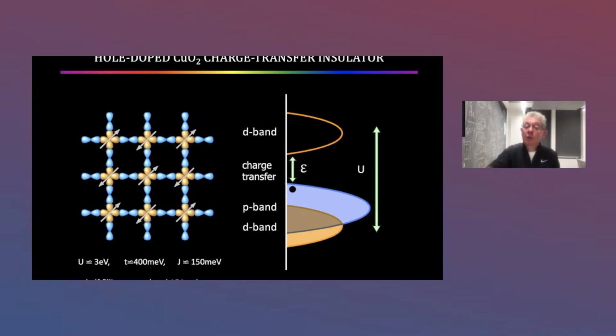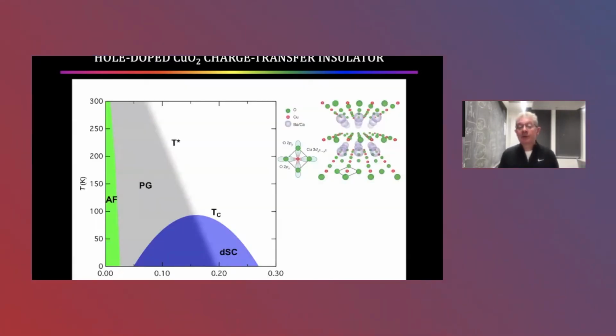But you can hole dope it. And hole doping, it's not like hole doping a semiconductor. What you're doing is removing an electron from an oxygen atom in the p band. And when you do that, transport begins. Some kind of a quantum mechanical state, which in my opinion is not fully understood, is created. But it allows transport through the crystal as soon as it appears. And we get this glorious phase diagram.